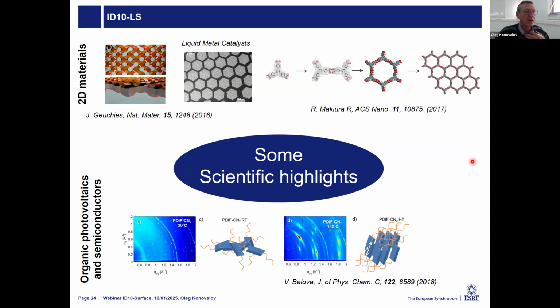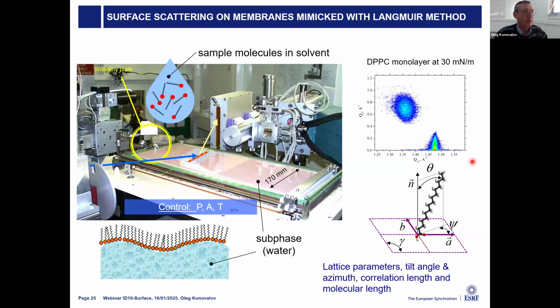So then, going to scientific examples, I will start first with some studies on liquid surfaces with the Langmuir trough, because this is mostly what we use, in-house and with users. Just 5 minutes, as we discussed. Okay, fine, good. From this type of measurements we can see the Bragg peaks, and from these Bragg peaks, as I told, we can find the length of the molecule, the tilt, and the lattice organization.